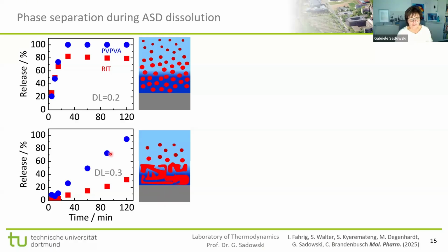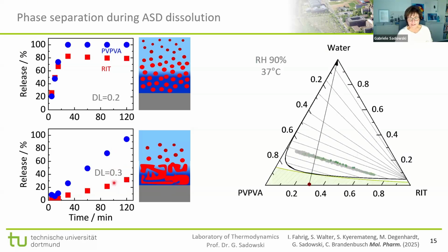So the problem is, how can we solve this problem? How can we overcome this situation? And the idea of our cooperation partner, let's add a surfactant. Indeed, most of the ASDs on the market do also contain a surfactant in addition to the polymer and the API. This is again still the phase diagram as before. These were our Raman spectra that we have taken from the samples for the 0.3 case, and the samples are very nicely in agreement with the tie line as before that we predicted.